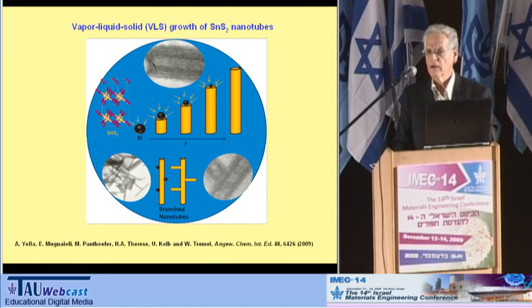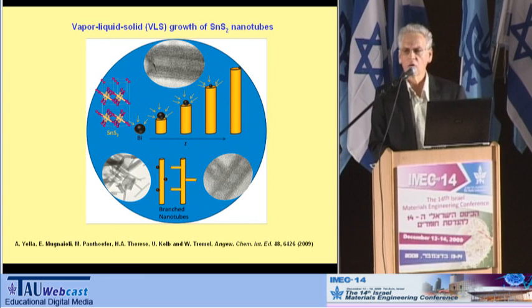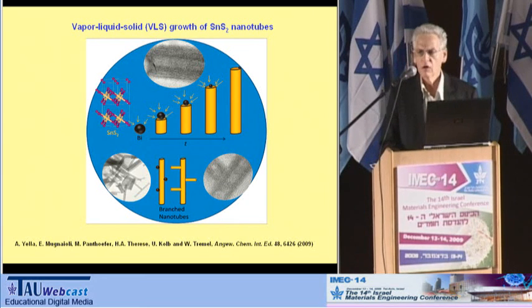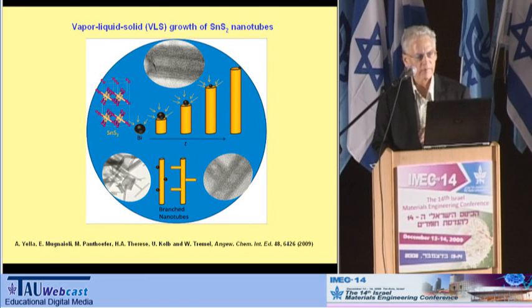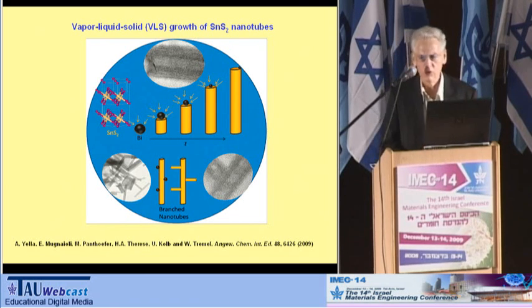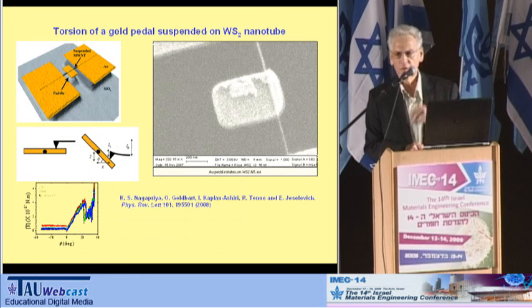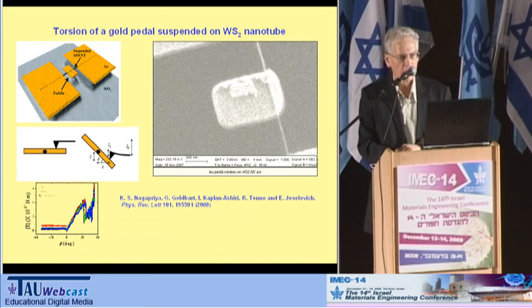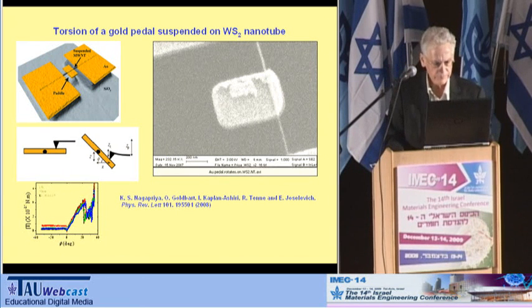Those of you that know the field know that Charlie Lieber from Harvard was the first to show that he can grow, continuously or in a very controlled fashion, nanowires of various materials using the catalyzed VLS process. And this is the first time that inorganic nanotubes are grown using VLS. In this case, it's tin disulphide with bismuth as the catalytic nanoparticle. And this, of course, gives rise to a lot of opportunities in terms of growth of new nanotubes.